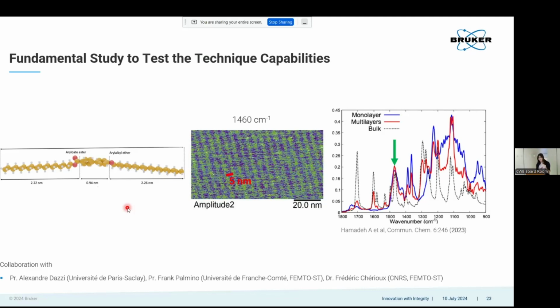And what you see when you have this is a material which is less than a nanometer thick, so about half a nanometer to 0.8 nanometers thick, that you can measure the spectrum on. So that's this blue curve over here. And when you map out at this wavelength, that's what this looks like, where the green is areas of intense signal and the purple is areas of lower signal. And you see this beating pattern, which corresponds to the length of the molecule itself. So you're seeing this self-assembled structure less than 10 nanometers, on the order of 5 nanometers across. And if you look at the signal variation, you're really detecting variation on the order of 1 or 2 nanometers. So that's really an impressively small size scale to be able to look at.